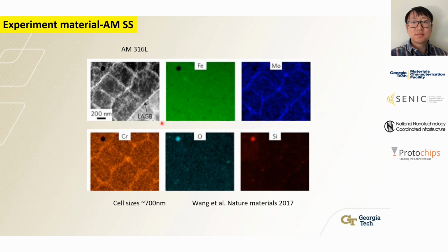This material has a unique property: if you look at this high angle annular dark field image, you can see there is a network with a bright contrast shown here. This network is due to the elemental segregation of molybdenum, chromium, nitrogen, and nickel. Sorry, this network is the dislocation cell network. In this sample, we can also see some big spherical spots. Those spots are oxide, mainly silicon oxide.